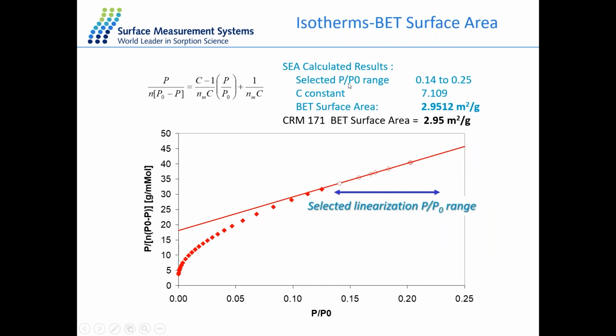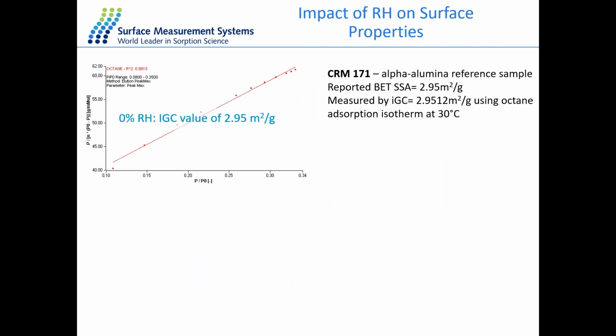This is another example of another aluminium sample, CRM 171, and again, we result in the same agreement with each other. With this sample, what we've done is calculate the BET surface area at different humidities. Effectively, we've run our experiment at 0% RH, resulting in a BET surface area of 2.9 meters squared per gram.